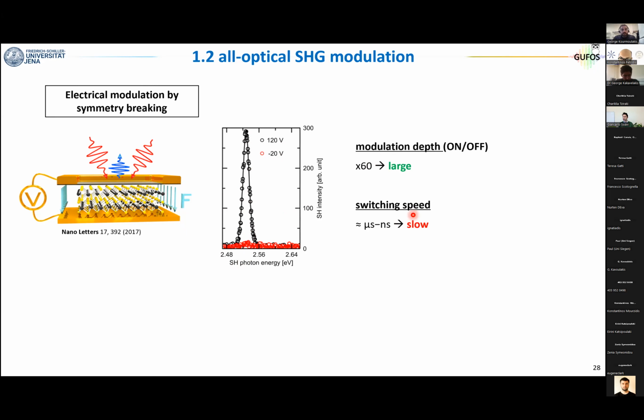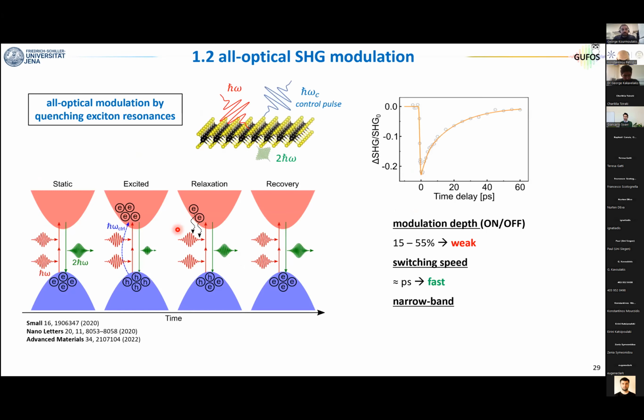The problem is that electronics is intrinsically slow. You can never switch on and off your signal at sufficiently high speed because you will be limited by your capability of switching this electric field that typically is at a maximum of nanoseconds. And that's why people go to the all-optical modulation. That is, you modulate the efficiency with an optical pulse. You see this graph reminds what I showed before about graphene. The time delay is the delay between the control pulse and the fundamental. Here, they're modulating the second harmonic in TMDs. You see now the dynamics are a bit slower. They are tens of picoseconds.